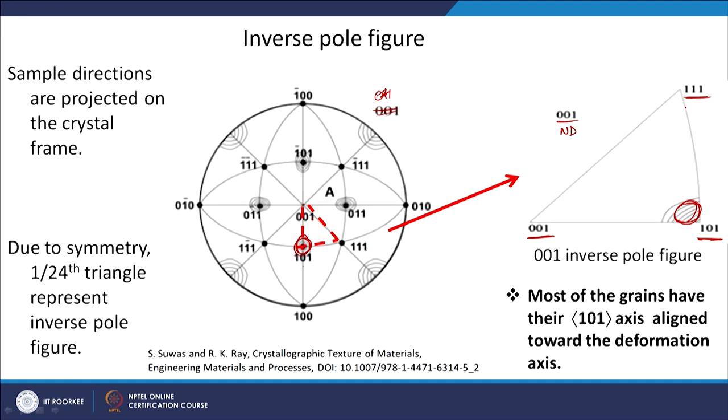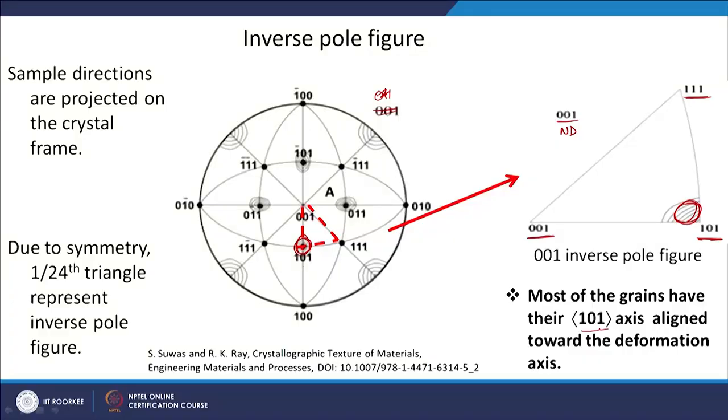So, this is slightly the opposite of what we do in the pole figure, where we have fixed the sample geometry and we are looking at how the unit cell is oriented, whereas in this case we are fixing the crystal frame, and we are looking at how the ND is oriented with respect to the crystal frame. As you can see, most of the grains have their 101 axis aligned toward the